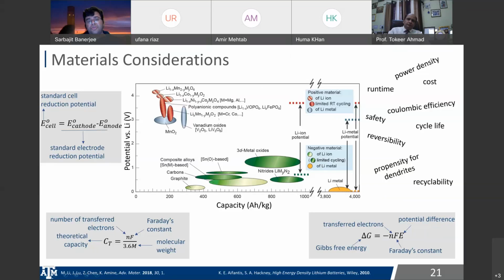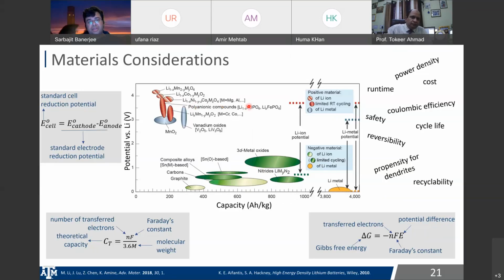We would like to move in this direction, right? Get cathodes to be higher voltage, higher capacity, and we would like to use our low voltage and high capacity anodes to the extent possible. So that's the dream. And again, the theoretical capacity is the number of electrons you transfer times Faraday's constant divided by 3.6 times the molecular weight, right? And again, the delta G, the Gibbs free energy, is related to the potential difference between the cathode and the anode, right? So that tells you how the thermodynamics is directly related to the cell potential.